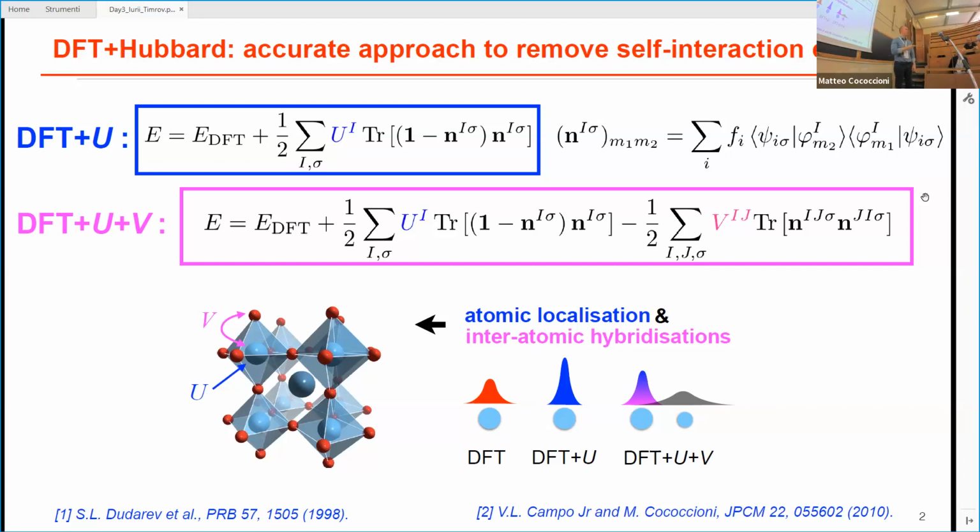So yeah, Matteo published a paper more than 10 years ago where they also tried to use the same approach, linear response theory, to compute J, and they did it for copper oxide because it was non-magnetic. But if you try to compute J with linear response theory for magnetic materials, there are some convergence issues, and also conceptual issues. We can talk with Edward more. So there is some work to do.